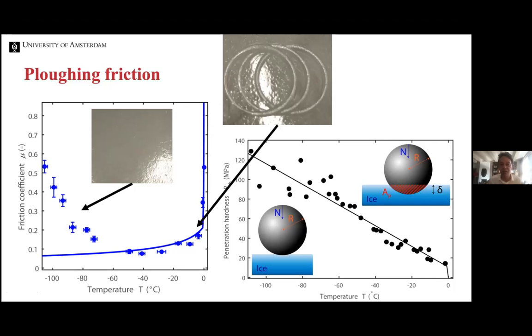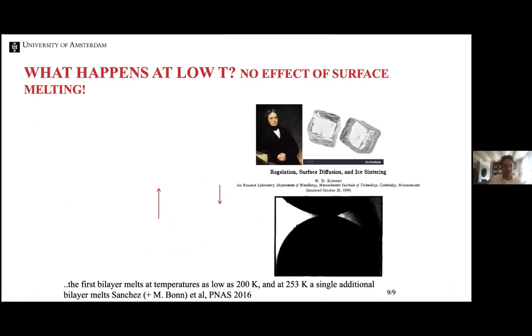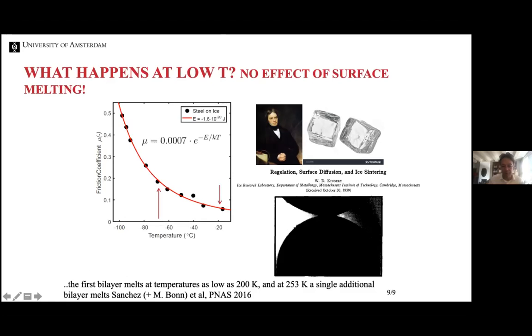Dutch children know this. You shouldn't go and skate on the ice when it's too warm, because it becomes really very difficult and you leave all these traces. The interesting question is now what happens here. And so this is where I got into a fight with my brother, because my brother is a spectroscopist and he looked at the surface of ice and he interpreted his spectroscopy data, in any case, in such a way that they found that the first bilayer of ice melts at something like -70, this arrow here, and at something like -20, the second bilayer melts. And so here you get the first thin water layer, and here the water layer becomes thicker.